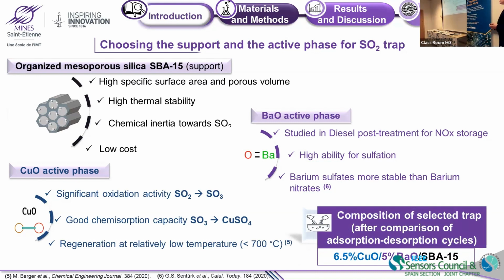So we studied the various compositions of this trap, and the percentage of active phases has been modified. After comparison of adsorption-desorption cycles, we chose the trap with the composition mentioned here: 6.5% copper oxide, 5% barium oxide, supported by silica. So I will show you the results obtained with this selected trap.